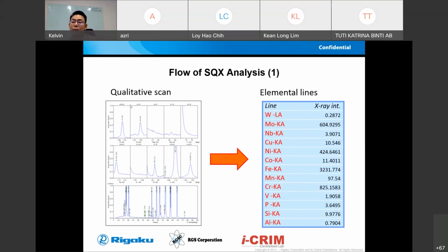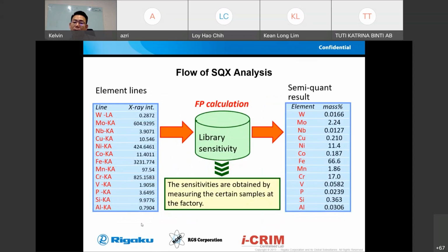So this information can be shown to you if you're doing the standardless analysis. Normally when we give the customer, we might give them this result and also this curve itself. This is for us to prove that this particular element exists in your sample. By comparing this intensity with the internal calculated theoretical intensity, if it converges, it gives you this semi-quantitative end result.